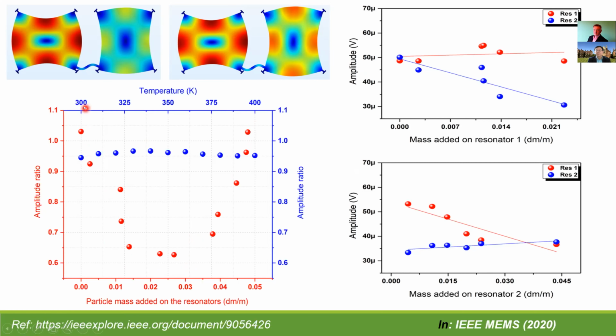But when we changed the temperature or varied the temperature, this amplitude ratio shift output metric stayed constant, which proved that this coupled MEMS resonator system is insensitive to temperature, but highly sensitive to the mass that is deposited on the coupled MEMS resonator system. So this proves the validity of using this coupled MEMS resonator system as a field deployment equipment for long-term measurements